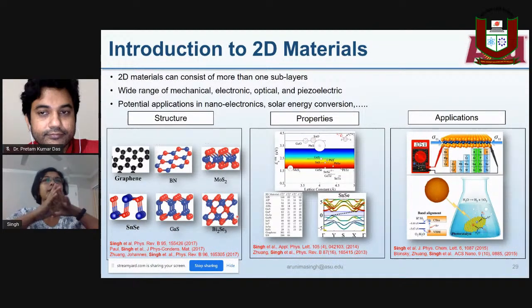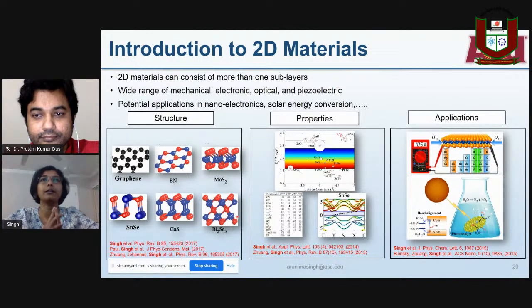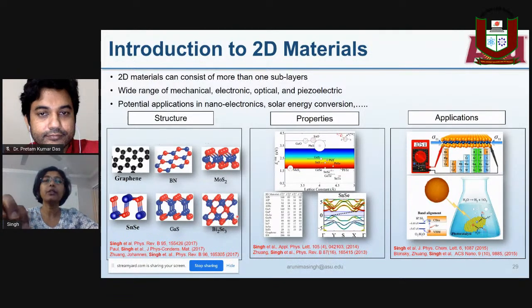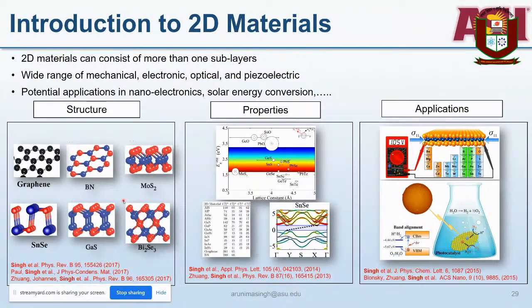Now, when do you say that it's not a 2D material anymore? If the thickness of your two-dimensional film is such that its property approaches that of the bulk, then it's not considered a two-dimensional material. And for these two-dimensional materials, there have been predictions of about 6,000 materials using theory and predictive simulations, and their properties, including their band gaps and mechanical properties, have a very wide range. They range from metals to insulators, from highly flexible to very rigid, and from very reactive to very inert materials. And they find applications as piezoelectrics, photocatalysts, nanoelectronics, and so on.